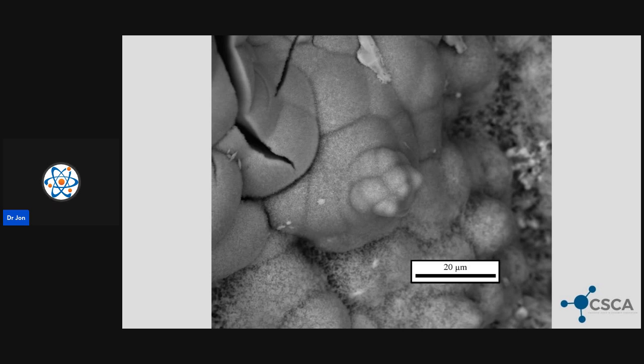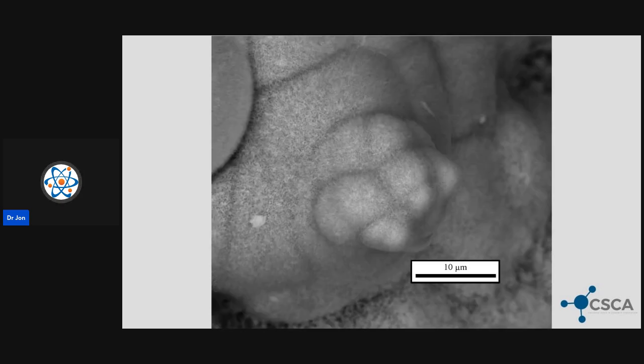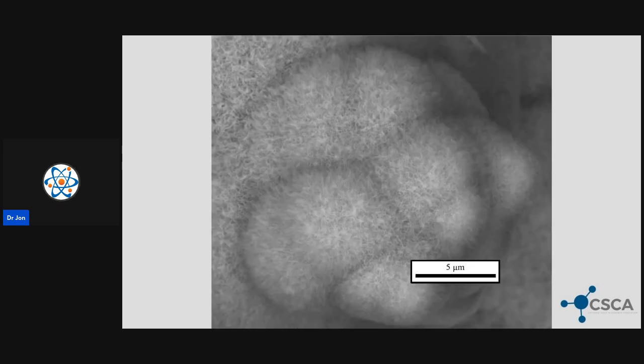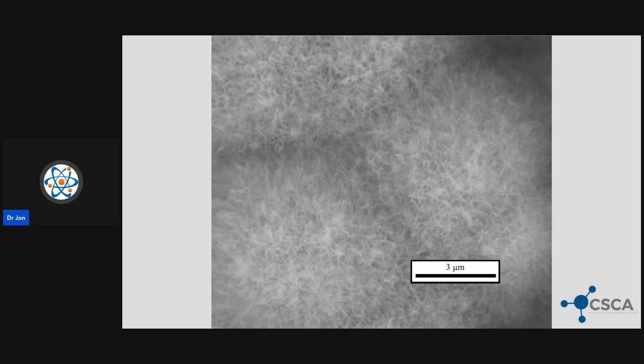Okay, so this is a higher magnification of that ASR gel rosette, and you can see I'm trying to focus on those little nodules there at the center. And as I get closer, and hopefully the image isn't lagging, you can almost see some of the individual fibril morphologies, these wispy needles that are interlocking. We're going to get a little bit closer, but this is the mechanism behind the ASR gel drawing in more water, and then having that ability not only to survive in that hydrogel-like state, but also thrive to go from a mature to a new gel or an immature state, which again is often contained within a shell that is then confined, that then creates more stress. And I think that's the highest zoom that I have on this. It's just so gosh darn pretty to look at those.